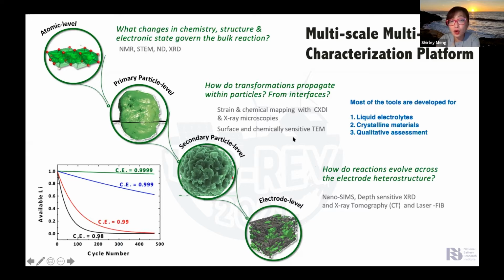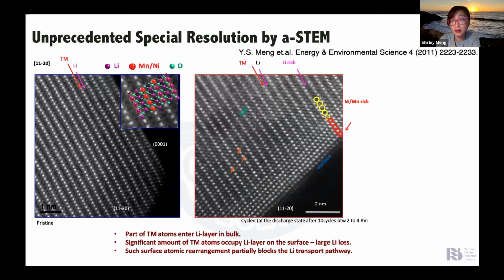We have to find ways for all these characterization tools to help us evaluate where the degradation mechanism is in the battery materials. This is one of the examples we have shown, in the layered lithium transition metal oxide. What you see here are real images of cathode materials made of lithium, nickel, manganese oxide. You can see the transition metals, nickel and manganese, arranged beautifully in these crystals. However, after very high voltage exposure, cycled up to 4.8 volts, you can see the phase transformations, especially in the surface layers of these oxides.